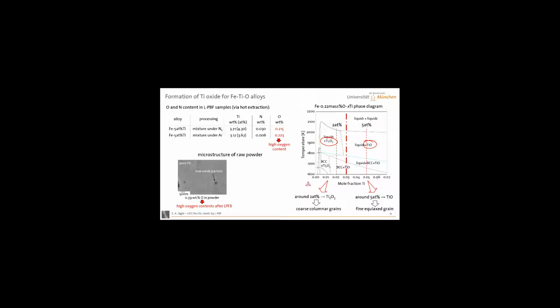So 0.2% oxygen, that's of course a lot. And it's not quite as much as we had in the powder. In the powder, we had almost 0.4%. So we're losing oxygen during the processing, but it is still a very high content. We would rather like to measure this in the low ppm. I will show later again this pre-alloyed powder that we purchased in a second step, and there we have 1 order of magnitude less oxygen content after L-PBF.